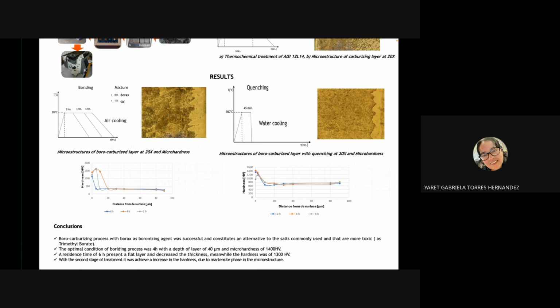A residence time of 6 hours presents a flat layer and decreased thickness. Meanwhile, the hardness was 1,300 HV. With the second stage of treatment, an increase in the hardness was achieved due to the martensite phases in the microstructure.